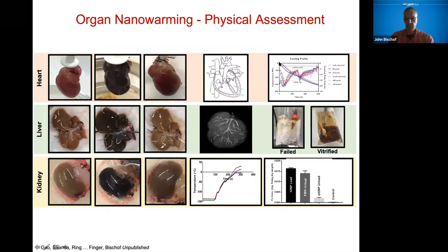And we've been able to demonstrate with all of them that we can cool them down to the vitrified state. We can demonstrate vitrification versus failure, which you see in these photographs on the right. We can study where the iron is within the system using advanced imaging. We can measure the nanowarming in the system, demonstrating that we don't have thermal gradients and that we're coming up sufficiently rapidly. And we can measure how much the iron is coming out of the system using ICP, mass spec, and things of that nature. And I'm going to just say, most is coming out, but not all. And this is, of course, an area for more study.